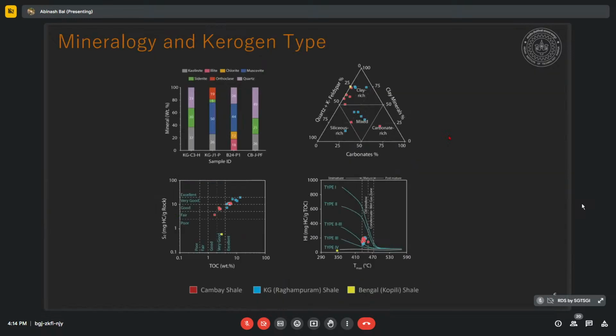Before that, we have to know what they are composed of. For that, we have done X-ray diffraction study for the mineralogy, and Rock-Eval pyrolysis for the kerogen study. In the XRD study, we have done a series of a total of 18 samples, but I am only showing four samples. Broadly, in the KG and Cambay basins, the primary clay mineral is kaolinite, whereas in the Bengal basin the primary clay minerals are illite, chlorite, and muscovite. If you plot in the ternary lithofacies, we found that the KG basin, represented in blue, is mostly mixed and clay rich, whereas the Cambay shales are mostly clay rich sediments.